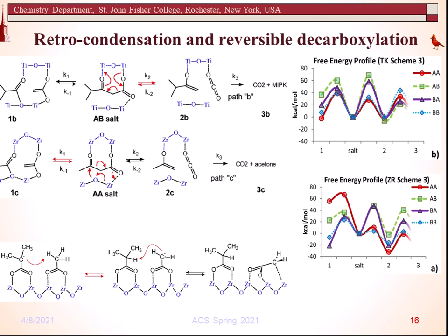and it's known in the literature that the enolate of a small size acid like acetic acid can lay parallel to the surface because it can bind to the surface metal center by the negatively charged alpha carbon. This bond is shown as a dotted line here. This is an additional stabilization which explains the low level of enthalpy for the species 1 when the enolized acid is the small acid A. For a larger size acid B, it would be more difficult to engage in such stabilization due to steric repulsion.